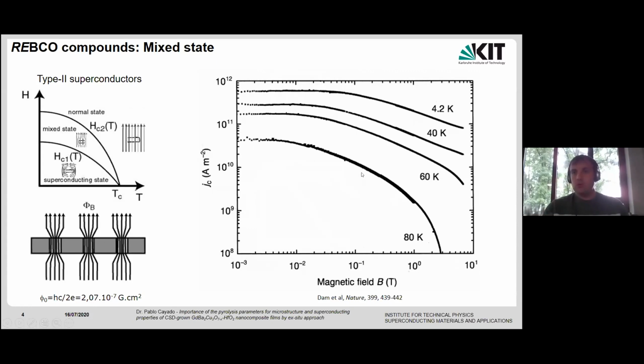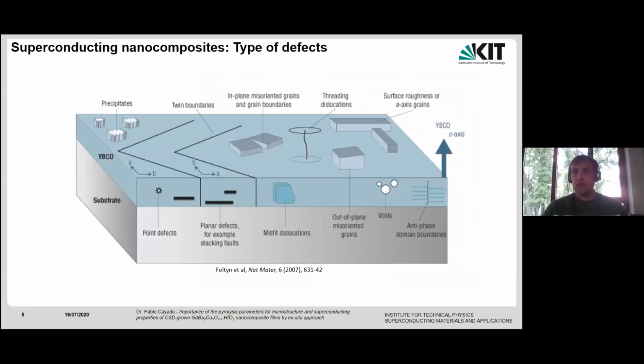So the way to prevent this movement and keep the properties high is to pin these vortices, and for this we need the defects that the REBCO compounds have inside. These defects, depending on their nature, can work in one way or another, but all of them can act as effective pinning centers. These are the types of defects that can appear naturally in the films or in the bulks also. But in most cases, they are not enough to really pin these vortices effectively. So what we are doing is to create artificial pinning centers by introducing secondary phases inside, for example, or creating these defects in an artificial way.